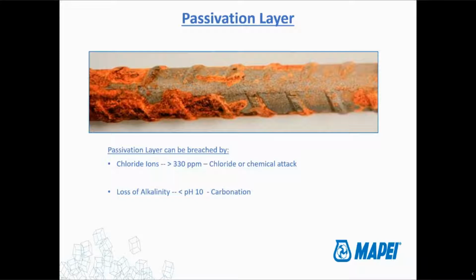The other manner in which the passivation layer can be breached is through a loss of alkalinity of the concrete. When we first mix concrete up, it's pretty high pH, so it's not uncommon to see a pH of 12, 12.5, even 13 in freshly mixed concrete. However, as carbonation occurs, which we're going to talk about in the next couple of slides, that pH starts to drop. So you start to get more of a balanced condition with the environment around the concrete. The pH comes down, and once it gets below 10, the passivation layer can be breached.